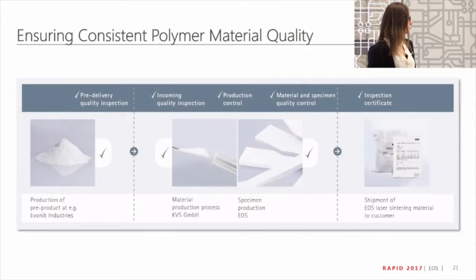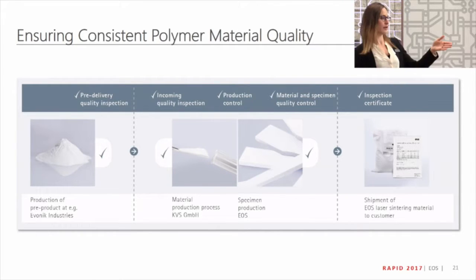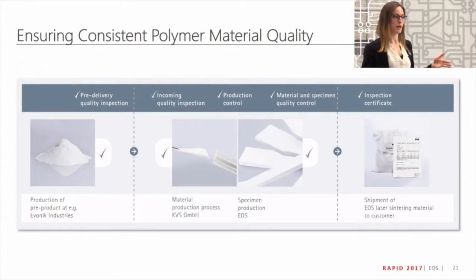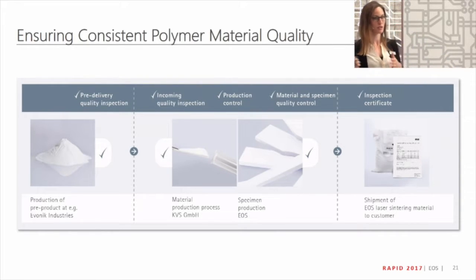And to do so, when we get powder in a pre-product, we have an incoming inspection, obviously. We have a production control for the compounding of the carbon fibers and everything we do. And we also produce specimens for every material batch. So we do tensile bars, we pull the tensile bars, we compare how that looks according to the database we have, and then you will get that overview, kind of a certificate of that powder batch every time. And that's really important when you think about production, and that's where we want to go.